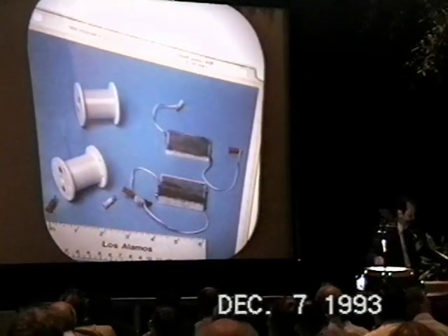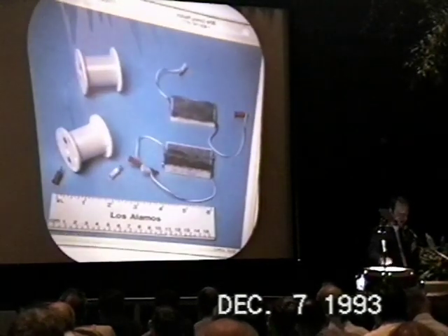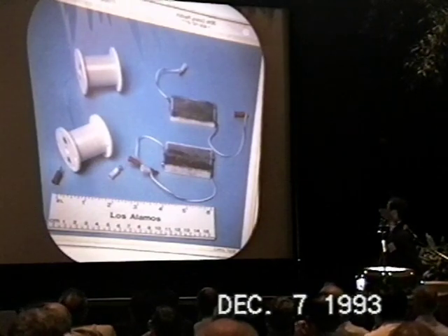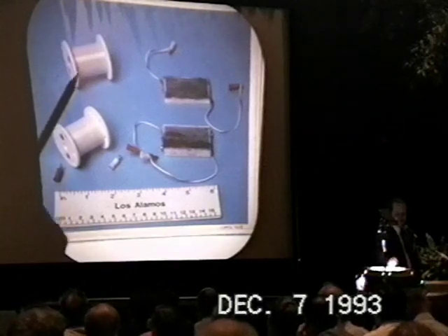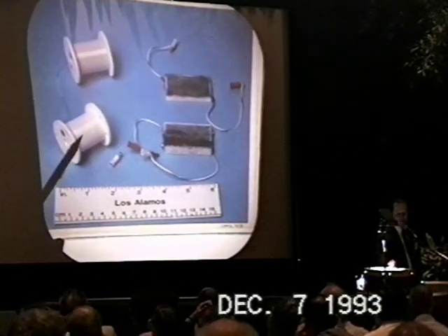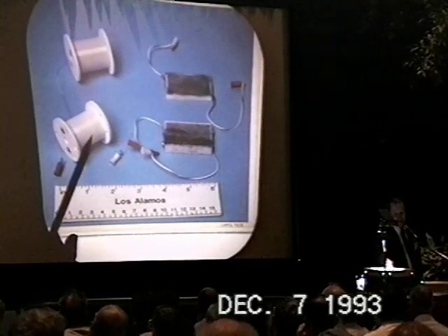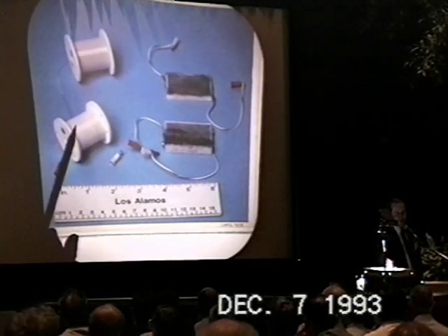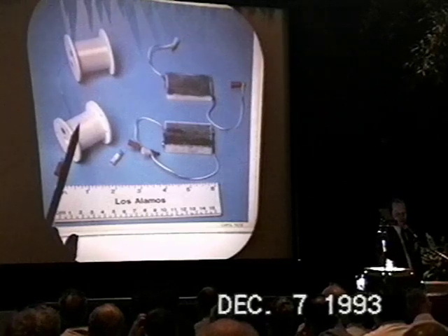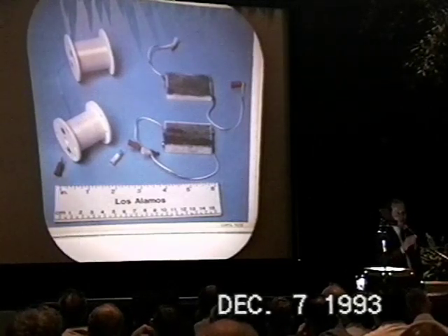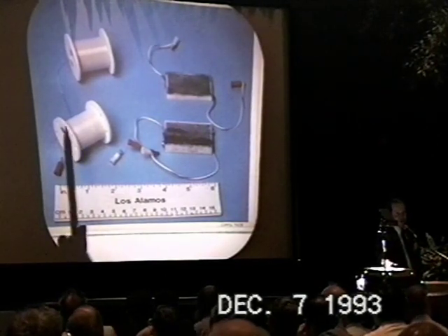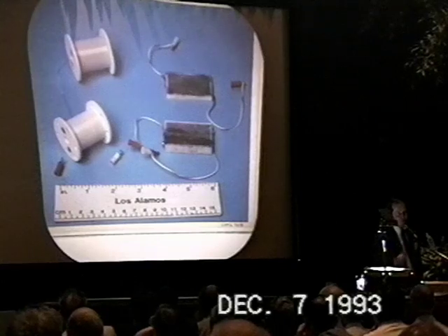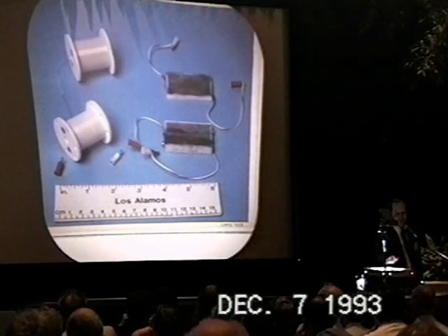This is a picture of the cells. It's not real visible. This is before you run, this is after. I don't know if you can notice that some of the wires have lifted off and moved up out of the track. We do believe that during the heating, probably with the high driving, there's thermal expansion. One of the problems you have is the wire touching the main cord as it's sticking out in the air. It's in this pulsing mode. As you heat it up, how fast does it cool down? And what is its average temperature?